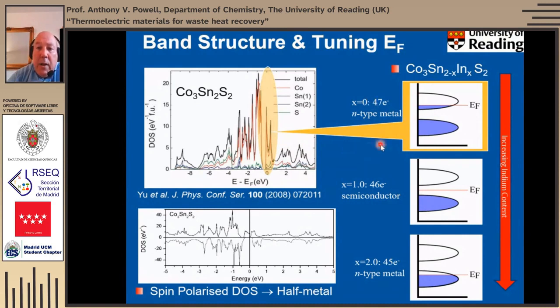And in fact, we can go, if we use something like indium, for instance, which each time we put an indium in, it removes an electron, we can go from a 47 electron material to a 45 electron material. And at the midpoint where we have a 50-50 tin-indium mixture, it's a semiconductor because the upper band is empty and the lower band is filled. And then if we go further, we start depopulating this lower band again.